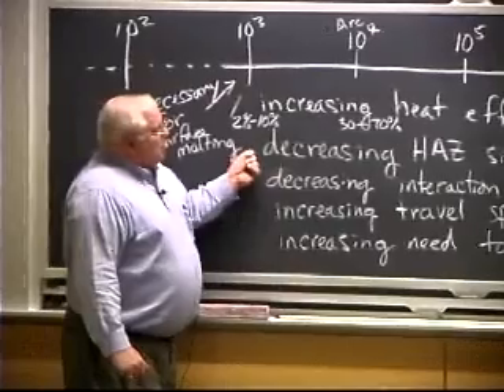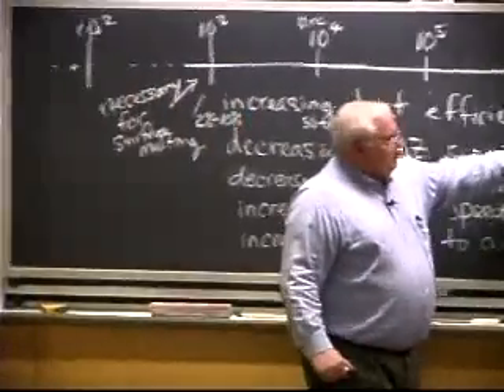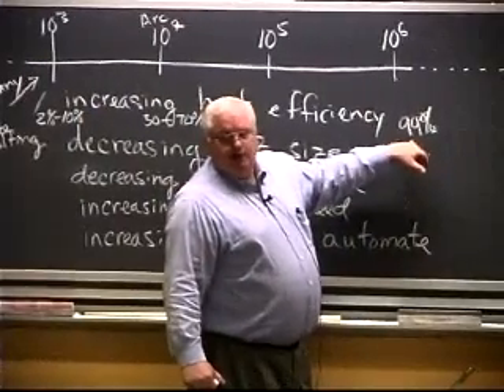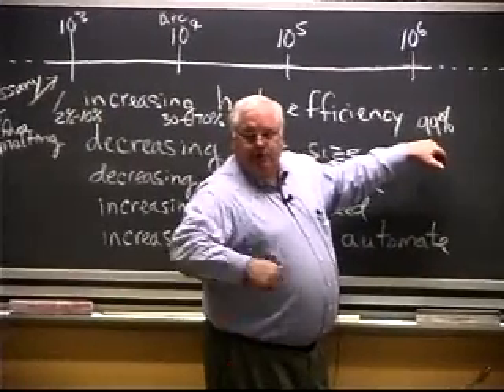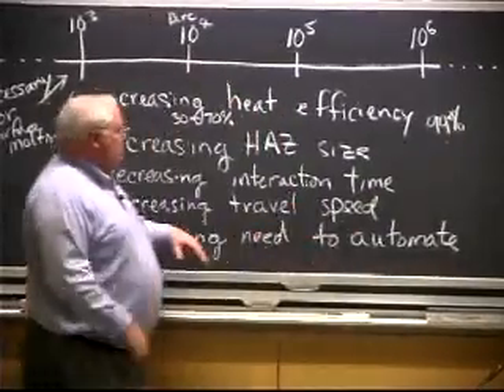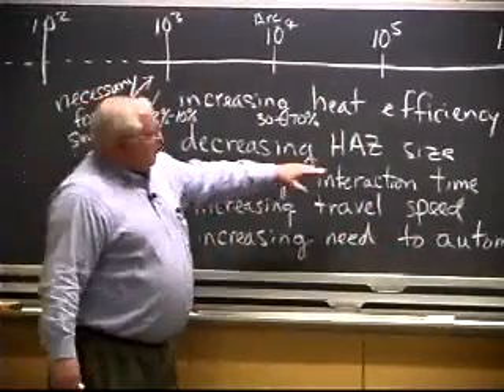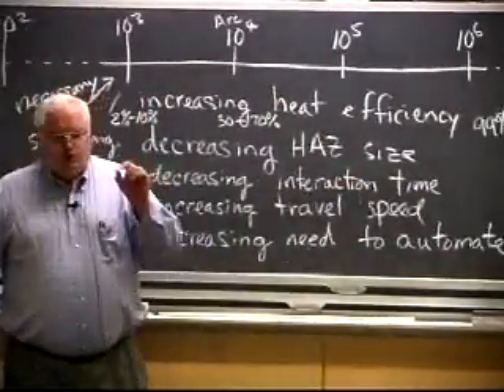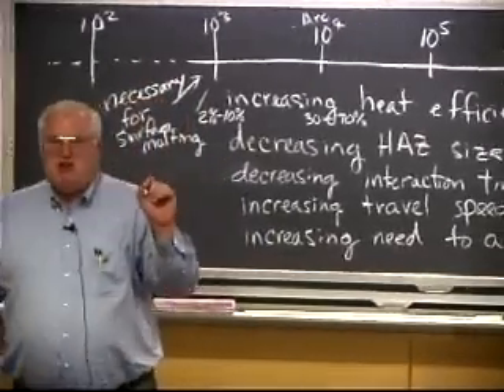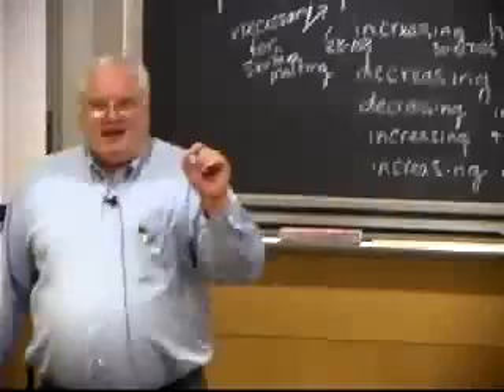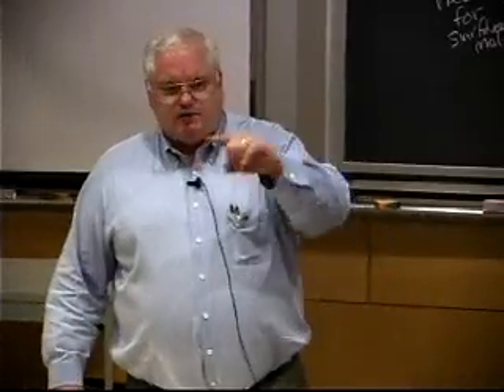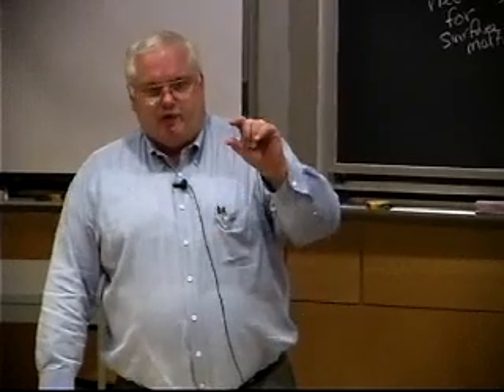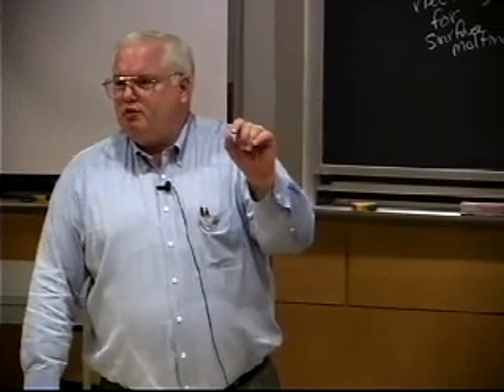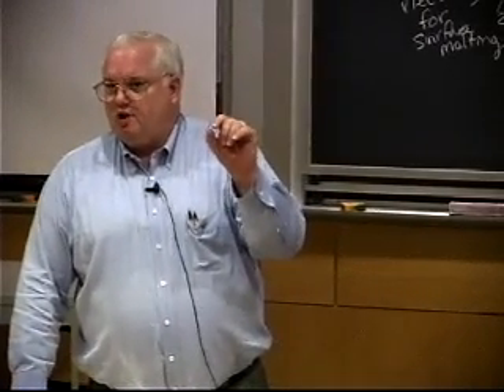You also, as you go over here, obviously if most of the heat is going into melting, you're not going to have a lot of waste heat heating up the surrounding material, and therefore what we call the heat affected zone, which is the material adjacent to the fused metal that has changed its structure. And I passed around steel welds before, that HY80 weld, and you can see a 2 or 3 millimeter wide heat affected zone on those arc welds.